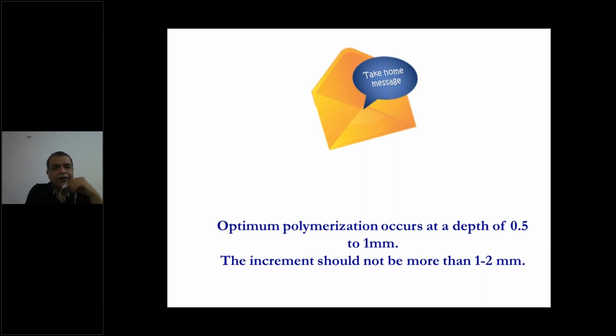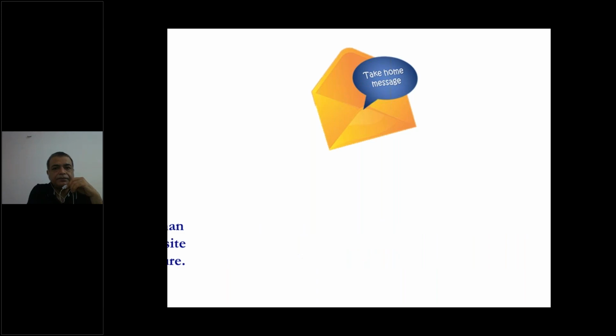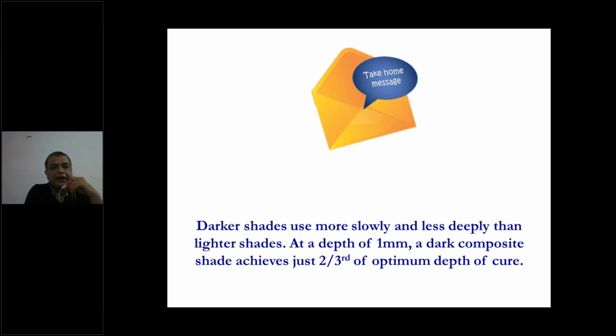As I have told you again and again, the increment should not be more than 1 to 2 millimeters, because that gives the optimum polymerization of composite resins. If you have thicker layers, the composite at the deeper layers may not cure well. Darker shades, you should be careful with them. They cure slowly and less deeply compared to lighter shades. And so if you're using darker shades, you can use a lesser amount of composite, or you can cure them for a longer time.